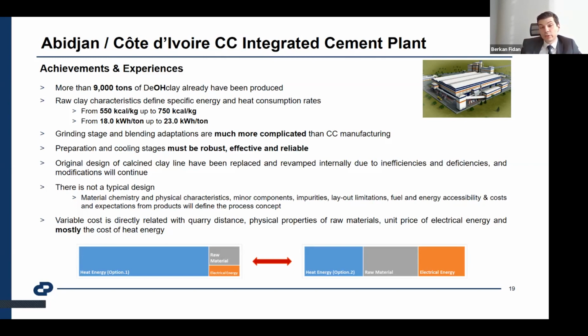One of the most critical points is that everyone talks about producing calcined clay, calcining, dehydroxylation and heat, but the more complicated part is creating a blended cement using calcined clay, because it's not a crystallized product and not homogeneous in physical characteristics. Some portions go very fine, the other stays coarse. It should be studied specifically, and we did that R&D and achieved good results. We can now control the water demand and other quality options. We are still investigating to improve it, but it's much more complicated. Preparation and cooling stages must also be robust, effective and reliable.